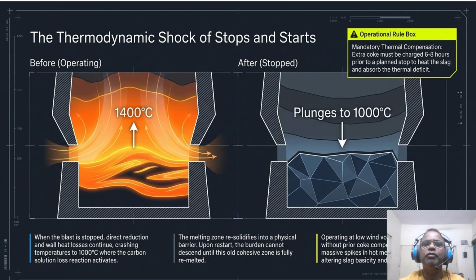Coming to our important aspects on the thermodynamic shock of stop and start. So look at the operating versus stop graphic. This is a very important graph. When the blast is on, we are at 1400 degrees centigrade. Within minutes of stopping, that temperature plunges to 1000 degrees centigrade. So the melting zone resolidifies into a physical frozen barrier in no time. So upon restart, the burden cannot descend until this old cohesive zone is fully remelted.